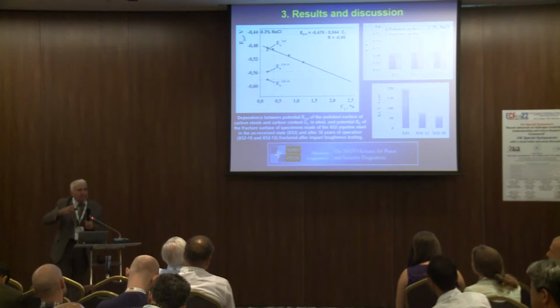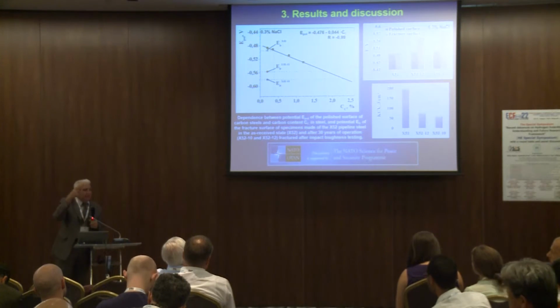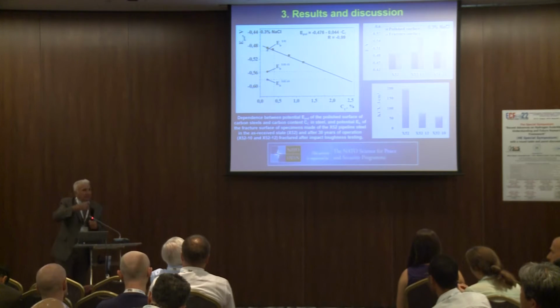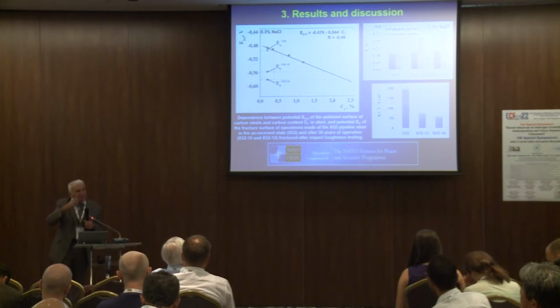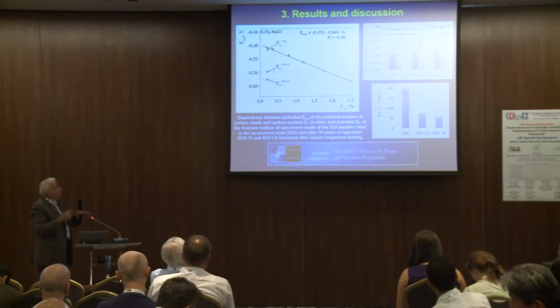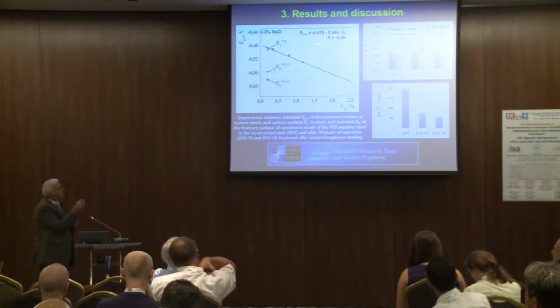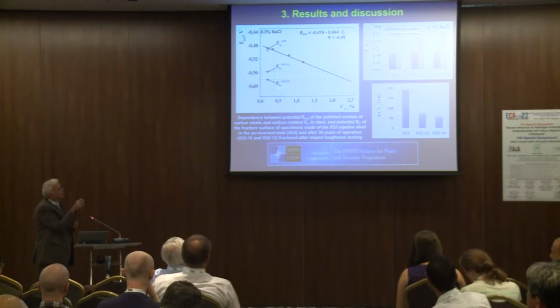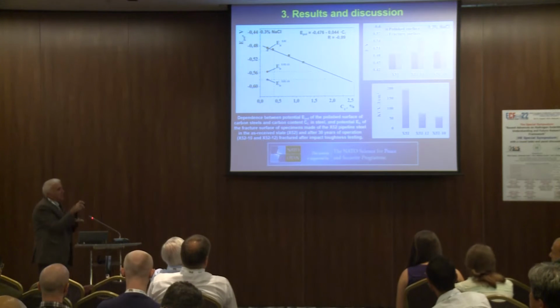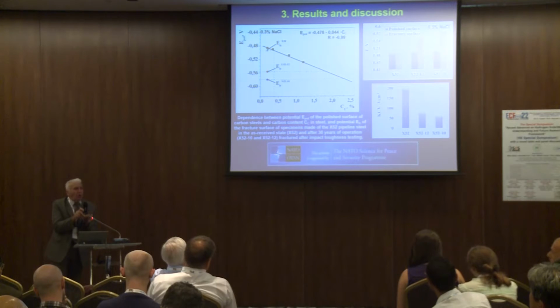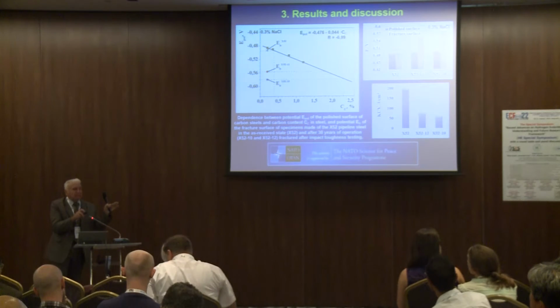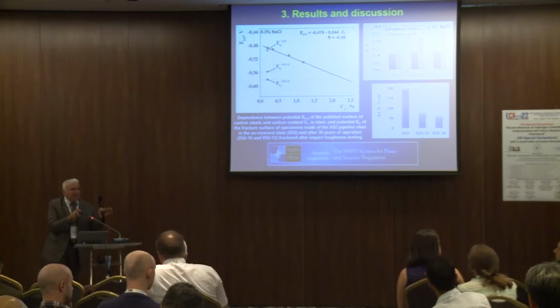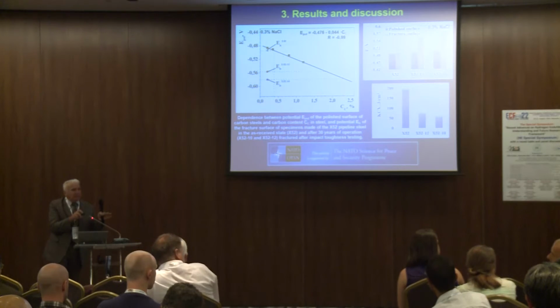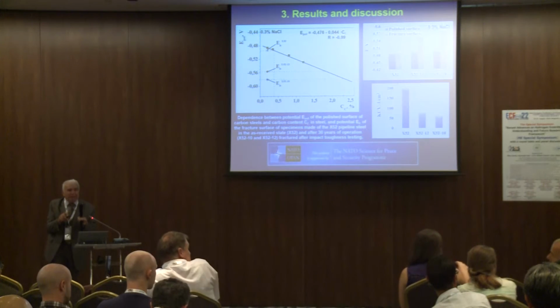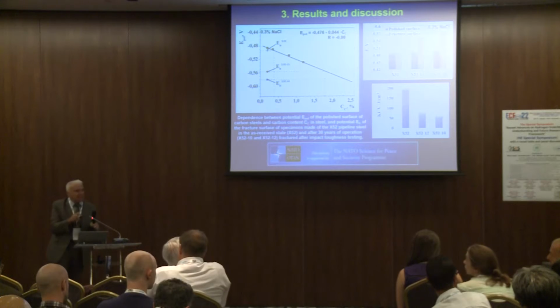It means that we have a correlation between impact strength and the shift of electrode potential measured on the fracture surface. Of course, this method allows us to predict such a level if we suppose that only this factor, carbide formation, is responsible for material degradation.